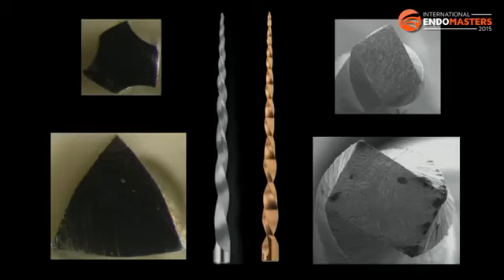Now, if we compare the primaries, on the apical diameter and taper, we had a 25/.08 with WaveOne, and now we have 25/.07 with WaveOne Gold. But also what we have is we have less taper coronally. So at the D16 with Wave.One, we had 1.2 millimeters, while we will end up with 1.135 with the Wave.One Gold. So you're cutting less dentine coronally, and you will have more conservation of canal dentine coronally. Of course, this is if you don't use any other file coronally.